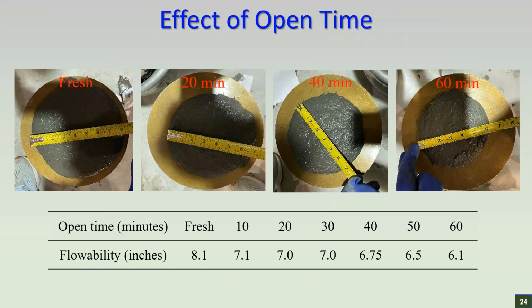So after selecting the mix which yielded a good compressive strength and low flowability value, the effect of open time was studied. For a fresh UHPC, the flowability is 8.1 inches, as shown in this table. As we observe the flowability of the mix at 10 minute time intervals, it reduces, and up to 1 hour, the flowability reduced from 8.1 inches to 6.1 inches. So basically, this effect of open time on this mix gives a very good window to work with the 3D printing.